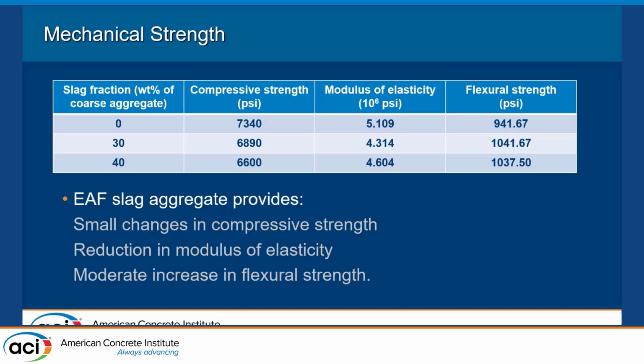So we also looked at some mechanical properties of concrete with the use of the slag aggregate. We did these tests with a base mix with traditional limestone aggregate, as well as mixes with 30% and 40% replacement, as the higher replacements would be the best economically and sustainably. So we saw that there were small changes in the compressive strength of the EAF slag aggregate concrete, as well as a decrease in the modulus of elasticity, which is hypothesized to be due to the more porous nature of the EAF slag when compared to traditional limestone aggregate.